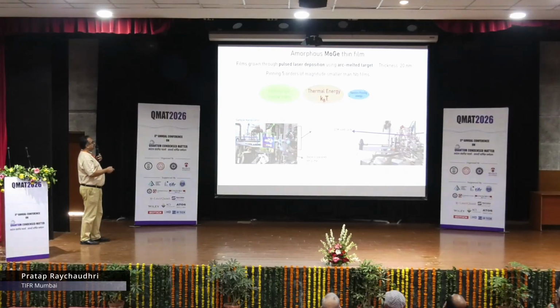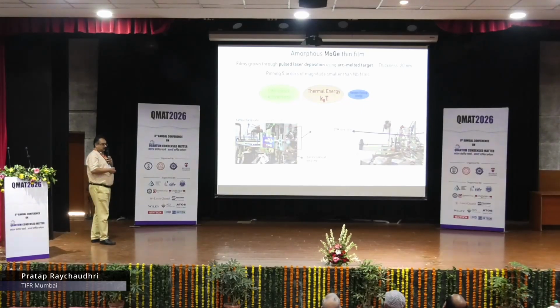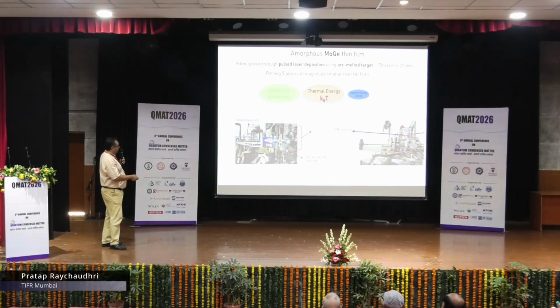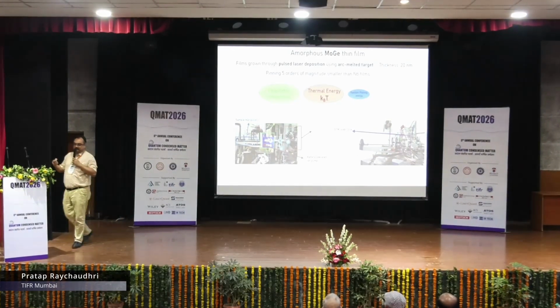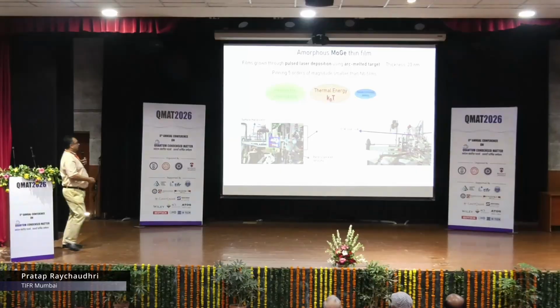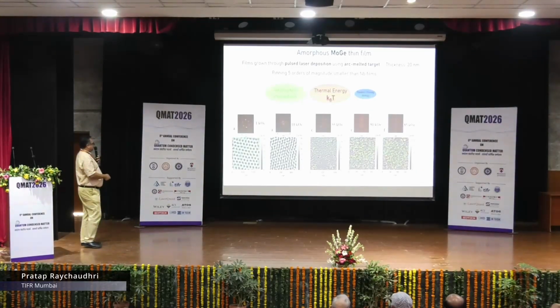This is a material that has been studied for many decades. However, no one did STM because the surface gets oxidized very fast. So we have this toy which is called an ultra-high vacuum suitcase. We grow the sample, directly take it in this suitcase, and then transfer to the STM without ever exposing it to air. Alright, this is the result.